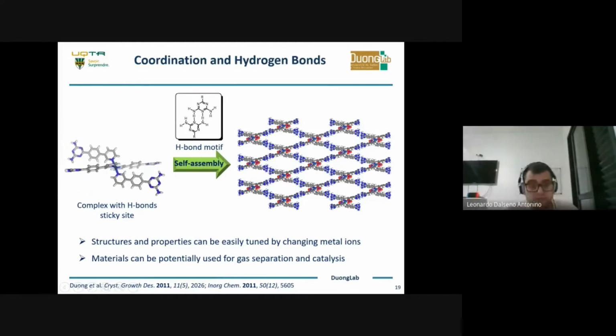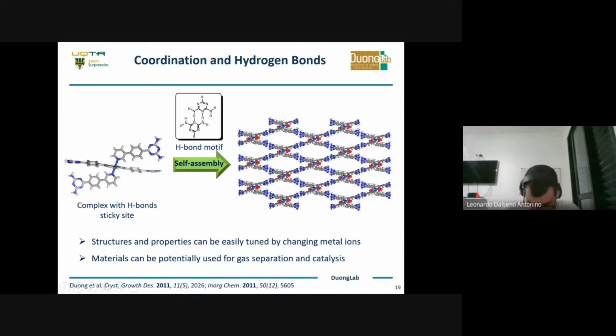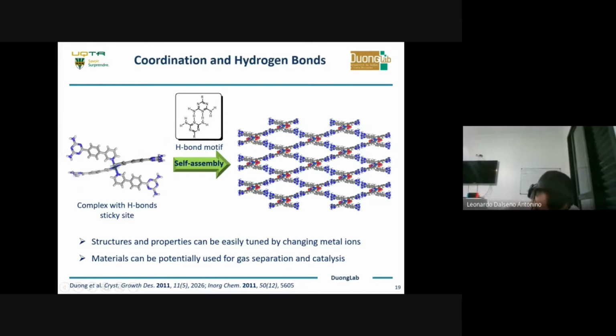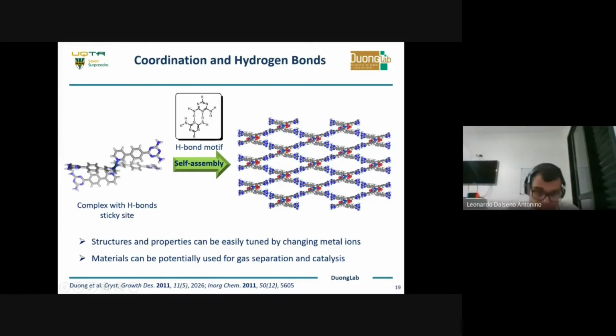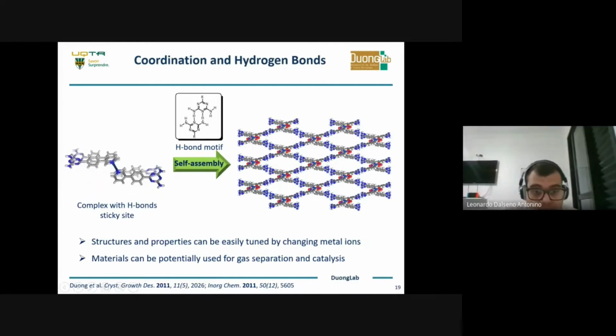And then at the extremity of the molecules, you add some sticky sites by hydrogen bond, and this is one type of hydrogen bond that is known to form. And what you see here, when we solve the structure by single-crystal X-ray diffraction, is a beautiful two-dimensional structure connected by hydrogen bonds and coordination bonds.